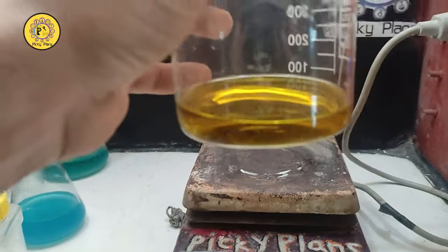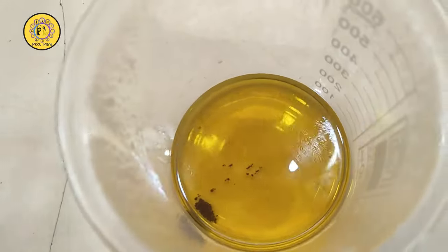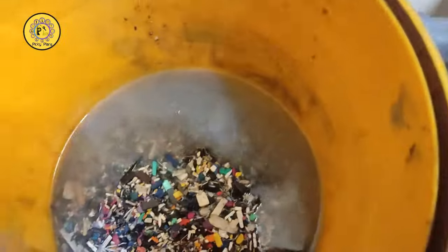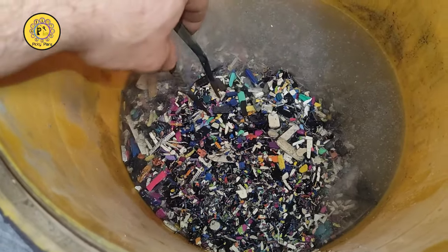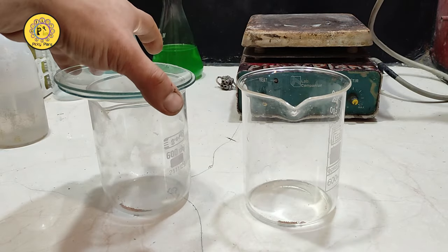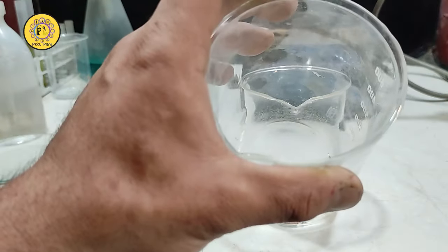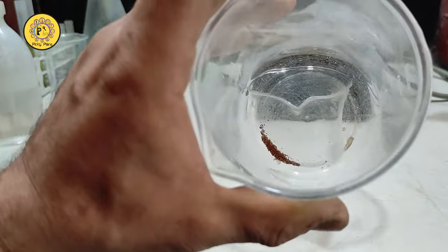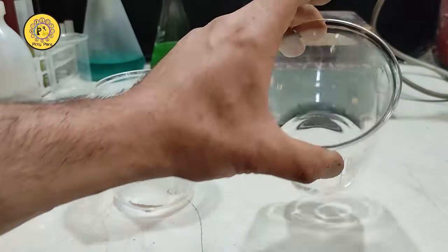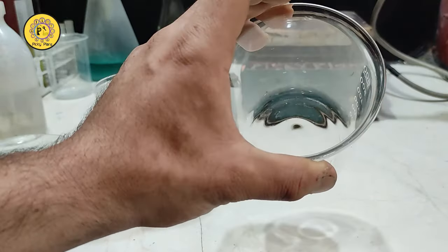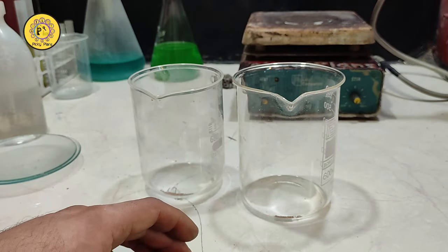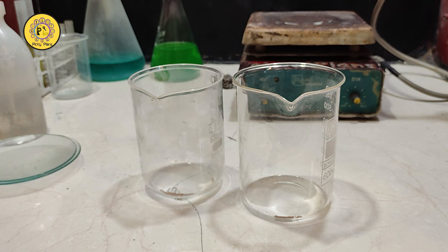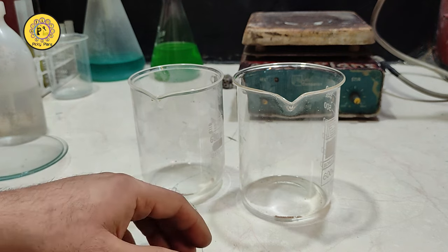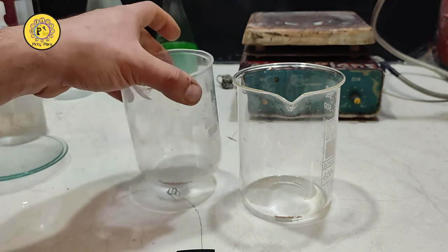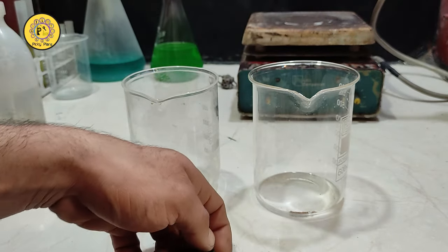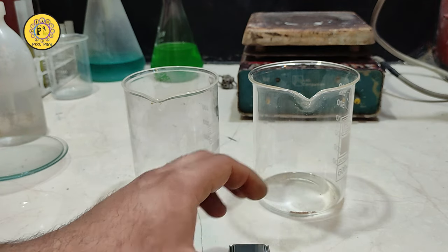Alright, this is the gold recovered from these stuff here. These are pins mixed with plastic. Here is the gold recovered through this process. Here is the gold from the clean and metallic portion of pins separated through the milling and washing. And here is the gold from the remaining pins in the plastic part. I'm going to weigh them together to see how much gold is possible to be recovered from more than 2 kilograms of pins, maybe 2.5. This was about 2 kilograms and some remaining in this, so I assume it was 2.5 kilograms of pins.